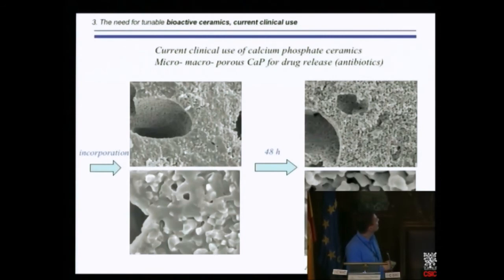So here is a large pore, and between the large pores we have a lot of microporosity. So we can fill the microporosity with antibiotic, impregnate it. So we can see here is antibiotic filling all the microporosities. And after 48 hours, not less, not more. Not less, why? Because if not, you have too much antibiotic at the same time. Not more, because if not, you have some resistance of the bacteria to the antibiotic. So with 48 hours, there is no more antibiotic in the bone substitutes.